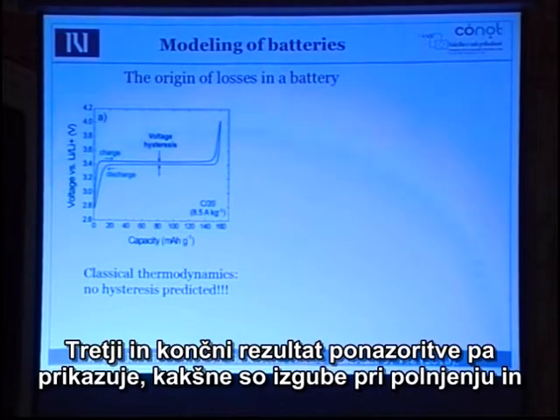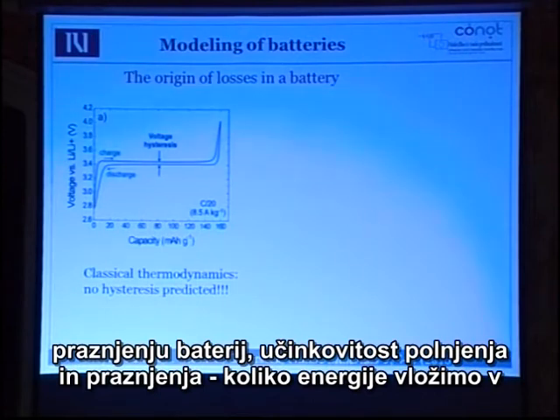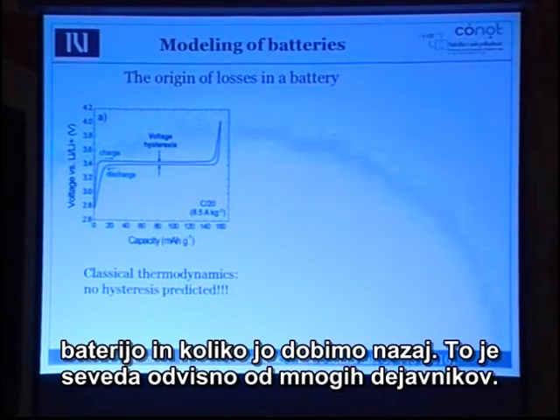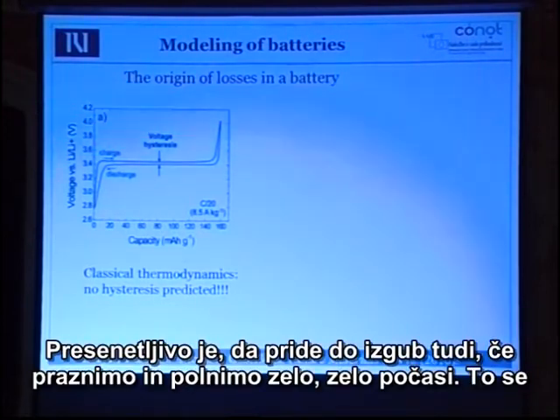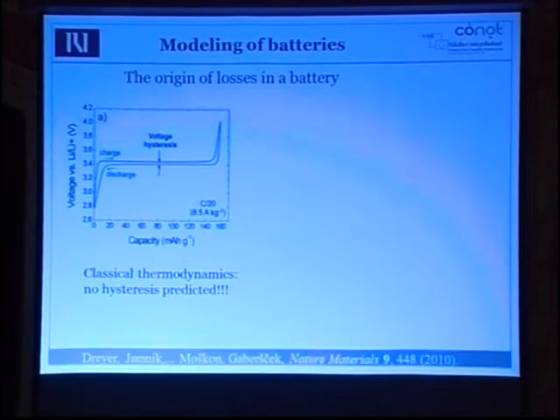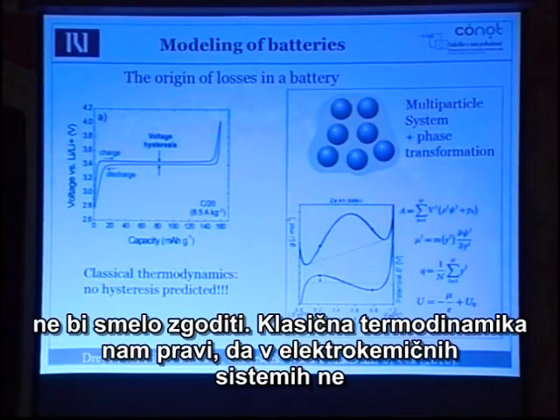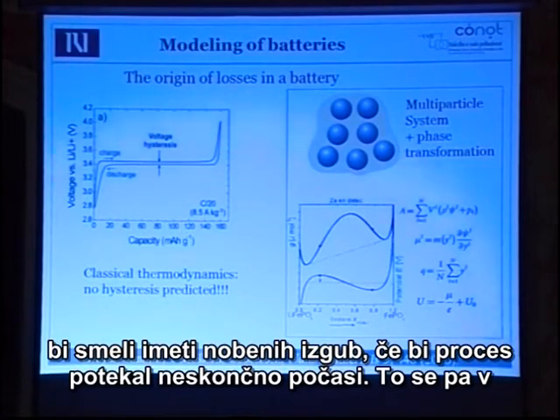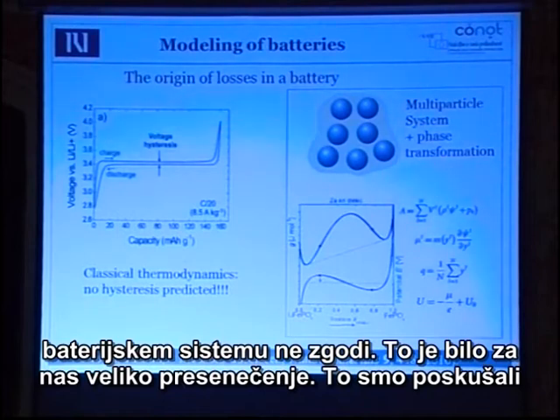Then, let's say the third and final modeling result: what if we have a battery and we charge and discharge, we need to know what the losses are. What is the efficiency of this charge and discharge? How much energy you put inside and how much energy you get out. Of course, this will depend on many factors, but the surprising part is that even if you discharge very, very slowly, you have certain losses. This shouldn't be. Classical thermodynamics tells you that in electrochemical systems, you shouldn't have any loss if you go infinitely slow. And this doesn't happen in battery systems. This was a big surprise for us.